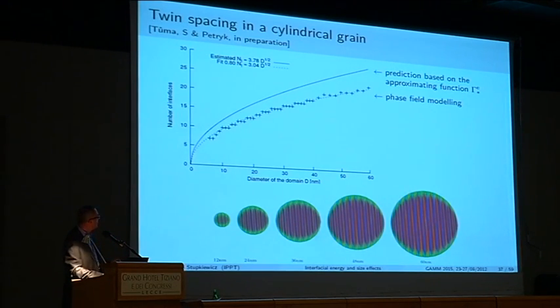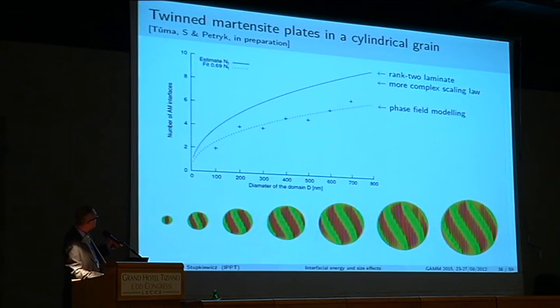Okay. And we can do a similar exercise for rank 2 laminate. So the scaling law is no longer a square root, but it's close to square root, and this is the result of simple modeling, and this is the result of phase field modeling. So here you see we have plates with substructure. And again, the scaling law is qualitatively the same. The difference is due to the same reasons, and maybe more about the small details that the phase field can really minimize the energy by updating the shape next to the interface so that the energy altogether is minimized.